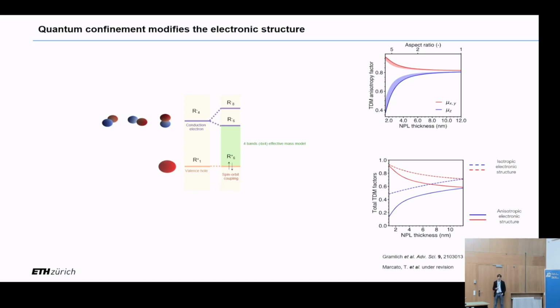It's shape dependent, okay? So as I depicted here, this TDM anisotropy factor is like the oscillator strength of the state. Well, it turns out in lead halide perovskite, if you decrease the thickness, the in-plane dipoles, so the states that contribute to out-of-plane dipole-like emission, they lose oscillator strength the more you confine. And this effect has to be combined with what we discussed before, with the effect of the dielectric environment. And if you do this, the picture changes significantly, even though please note that the anisotropy factor actually depends on the ratio between these 2 quantities. So in weakly confined nanocrystals, the effect is minimal, but you can see a big change in thin nanocrystals.